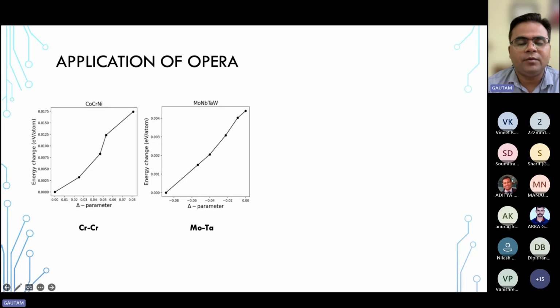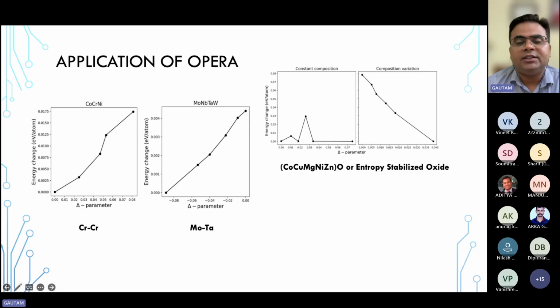Similarly, for the refractory high entropy alloys, if you increase the molybdenum tantalum propensity, the lambda parameter goes negative, because that's an unlike bond and the energy goes negative. We have applied this to study chemical short-range order in high entropy oxides also.